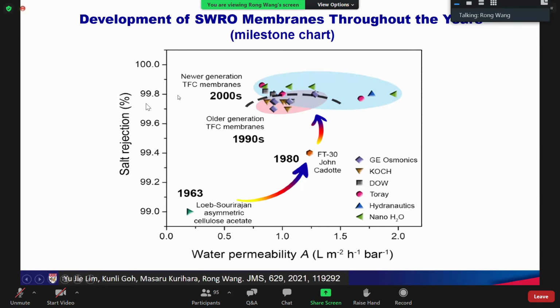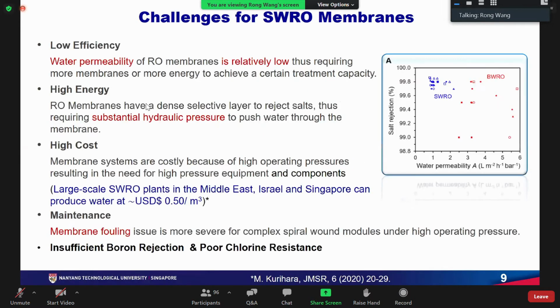Those membranes have very good salt rejection, over 99.7 to 99.8%. You see here, the water permeability is around 1 to 2 LMH per bar. However, the further exploitation of this technology is limited by the relatively low water permeability and the high specific energy consumption required, which multiplies to high unit cost for water production. In addition, membrane fouling, insufficient boron rejection, and poor chlorine resistance are the challenges for SWRO membrane development.